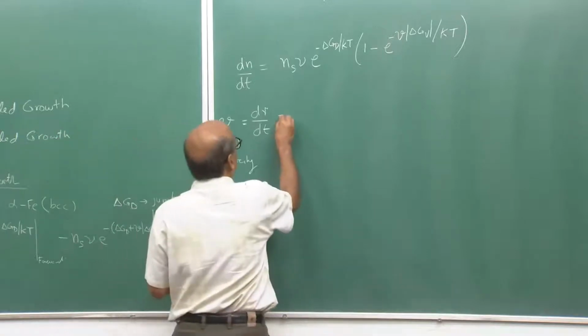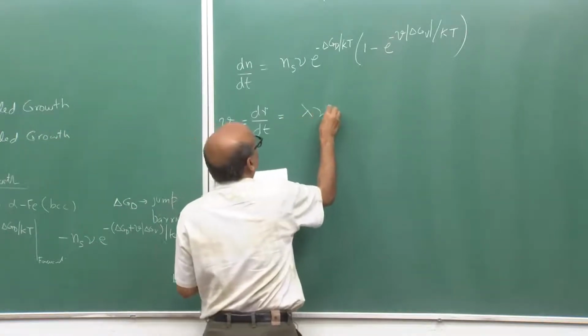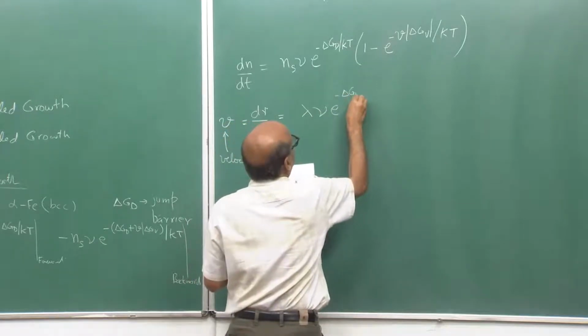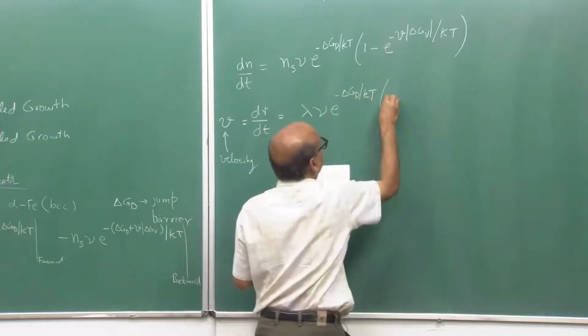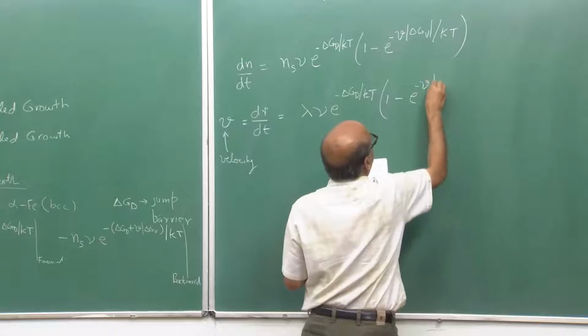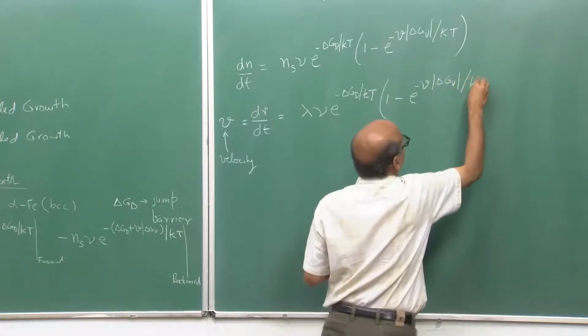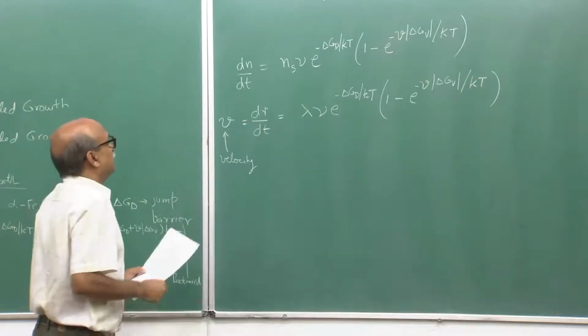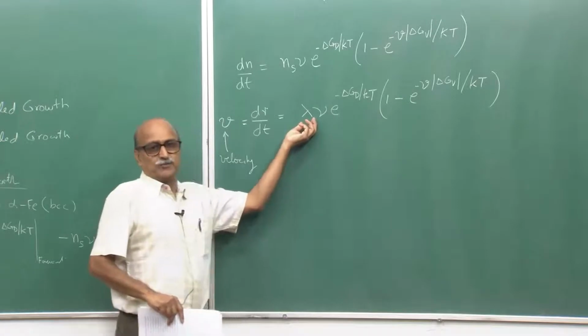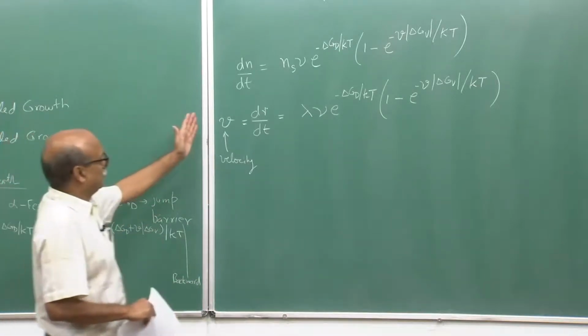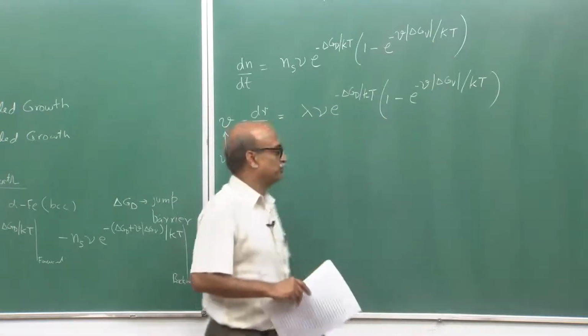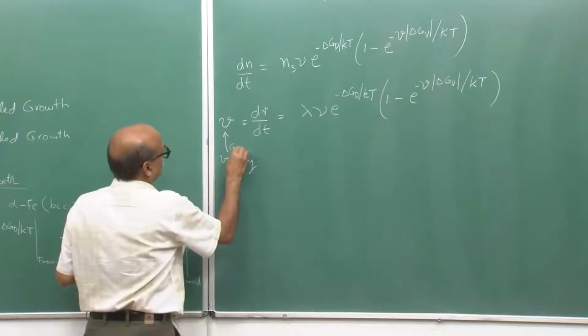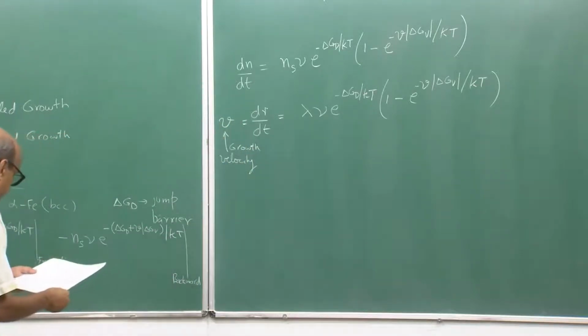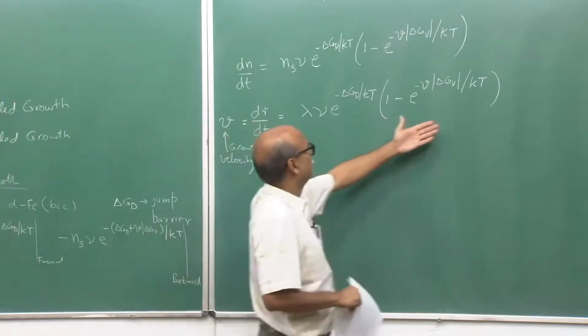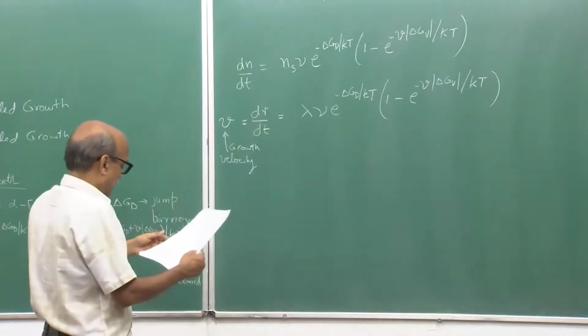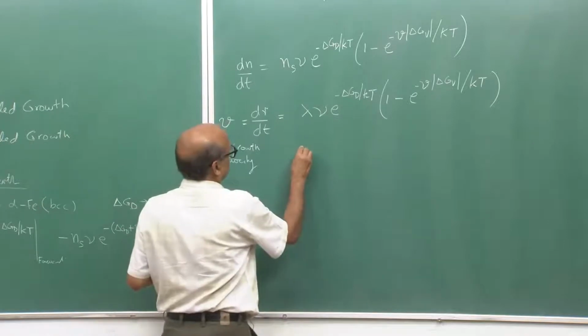dr by dt can be written, in a very similar way, as lambda nu e to power minus delta GD divided by KT and the same bracket term 1 minus e to power minus V delta GV divided by KT. Here lambda is essentially the atom to atom distance, and hence we are able to now write growth in terms of a growth velocity. So, this could be considered as a growth velocity. If I look at this expression, we can try to see what happens for small driving force.